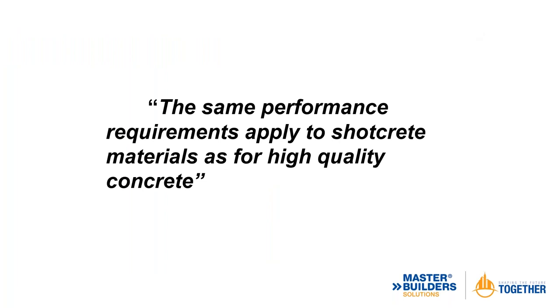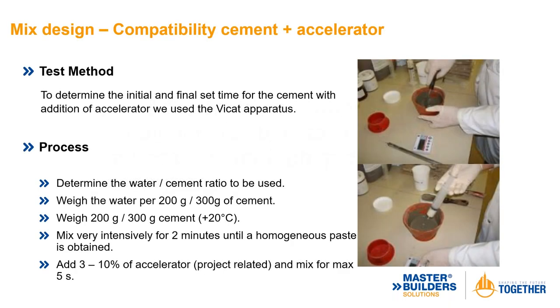As a mentor of mine, George Yagi, said: the same performance requirements apply to shotcrete materials as for high-quality concrete. Shotcrete is very high-quality concrete — very close to an SCC mix due to the water-cement ratio and amount of cementitious materials. When first looking at a mix design on site, we check early strength to ensure cement and accelerator are compatible using a Vicat needle. We determine the water-cement ratio — typically 0.38 to 0.42, as high as 0.45. Weigh water and cement, intensively mix for two minutes until homogeneous, add 3 to 10 percent accelerator (nominally around 8 percent), and mix for a maximum of five seconds.